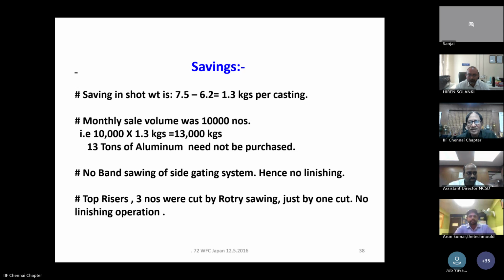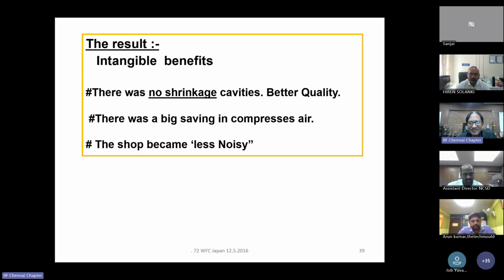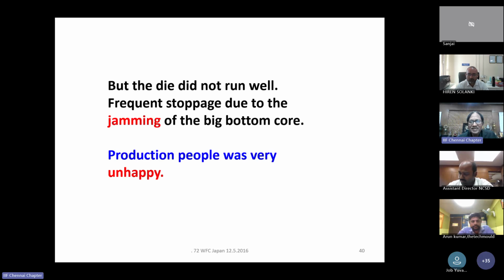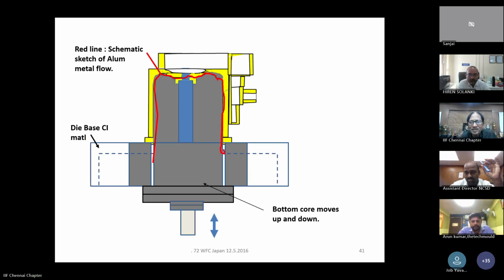That is the saving. But the story at the end there. Lot of intangible benefits were there, no shrinkage cavities, no need for the compressed air. But the catch is there is always a problem. The die did not run well in operation. Why? Frequent stoppage due to the jamming of the big bottom core, because molten metal enters into the core. The big problem. Production people were very unhappy. The solution was not accepted for production because of the operating problem.